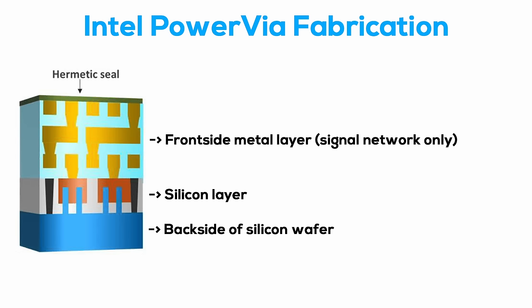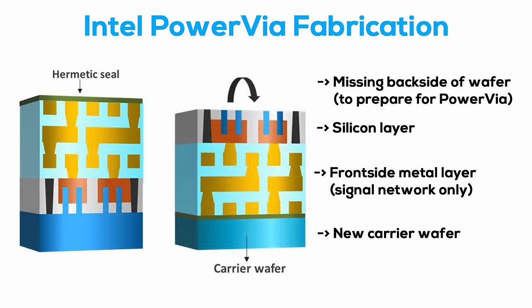It's here where the production process of backside power delivery really starts to deviate, because a second silicon wafer, also called carrier wafer, is introduced. This wafer is bonded on the top of the front side and placed right above the hermetic seal. This carrier wafer doesn't contain any active silicon. It's only used for structural support, because in order to prepare the original wafer, the one with the transistors, for backside power delivery, all the silicon on the backside of this wafer, which was previously used for structural support, has to be removed to reveal the backside contact points. This means the original wafer loses its function as structural support, hence the introduction of an additional carrier wafer.